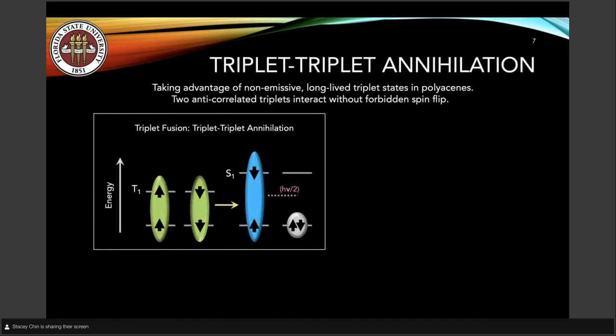The upconversion occurs through a process called triplet-triplet annihilation. What we do is take advantage of non-emissive and very long-lived states in polyacenes, so a lot of carbon, a lot of hydrogen, and a lot of double bonds. In this upconversion process, two anti-correlated triplets interact without a forbidden spin flip. Essentially you take one spin up triplet, one spin down triplet, and in the end you get one higher lying singlet state and a ground state.